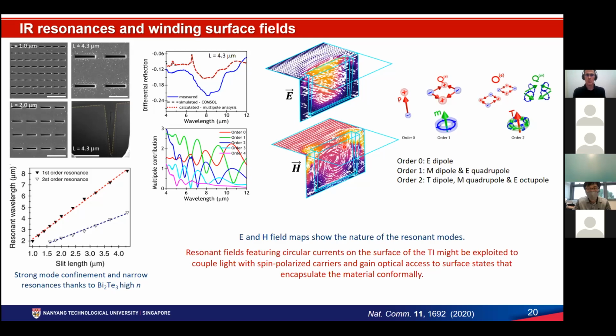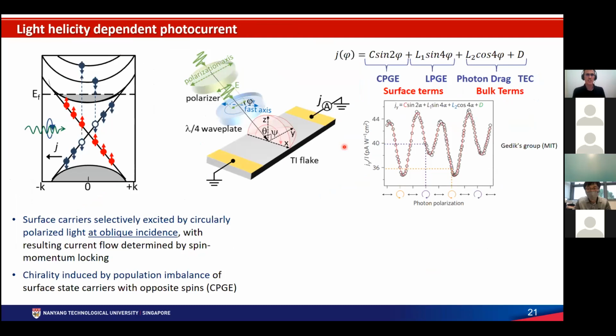However, all the examples I showed up to now basically fail in showing that you can engage solely the surface of the topological insulator. So we decided to change perspective a little bit, and we relied on the fact that topological insulator carriers have a very unique dependence on the light helicity when you illuminate. So they can selectively be excited by circularly polarized light. If you come at normal incidence, you will not be able to excite selectively surface carriers with a specific spin. But if you come with oblique incidence, you will be able to selectively excite carriers with a specific spin, and therefore you will be observing topological transport.